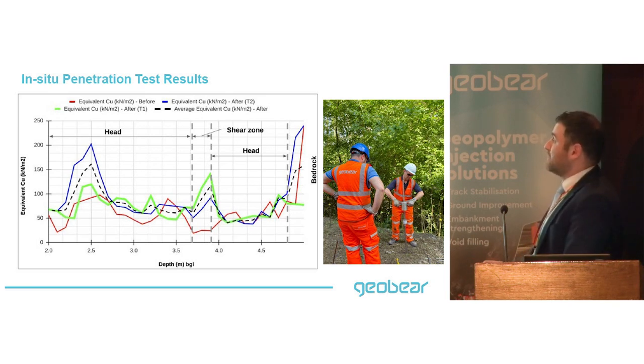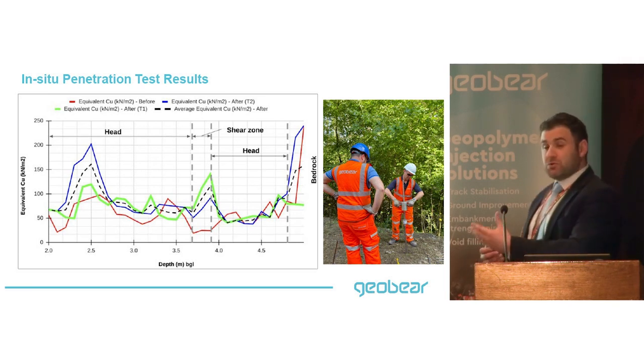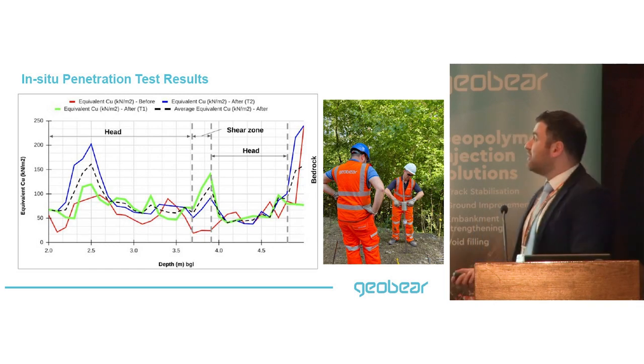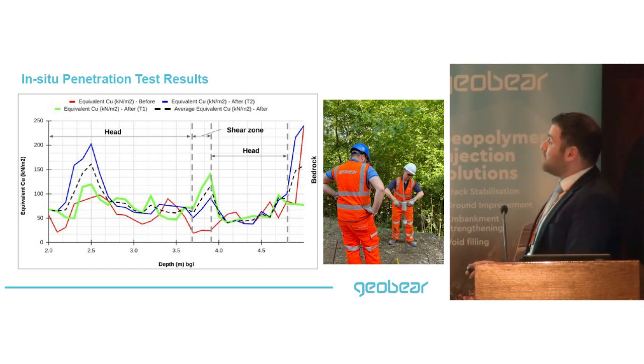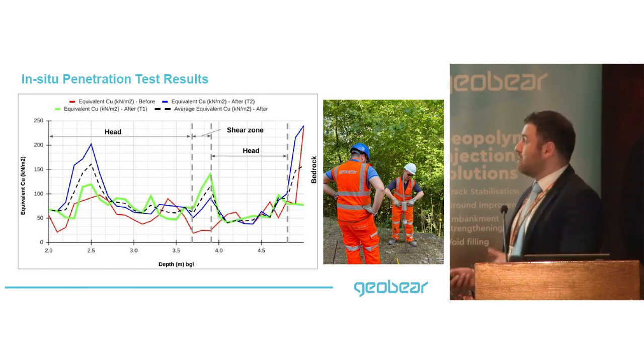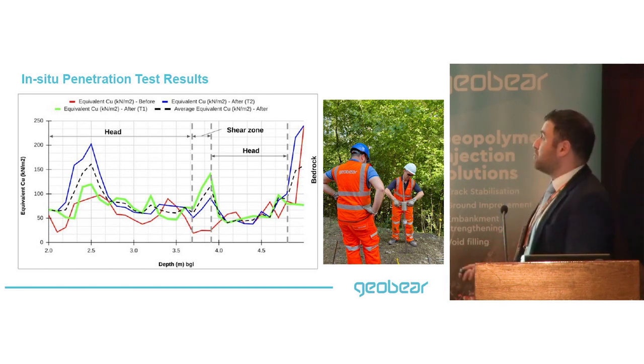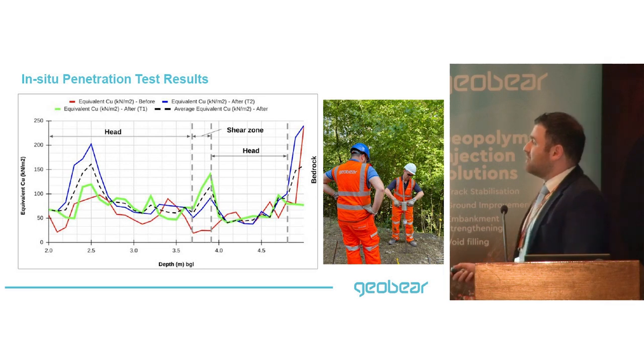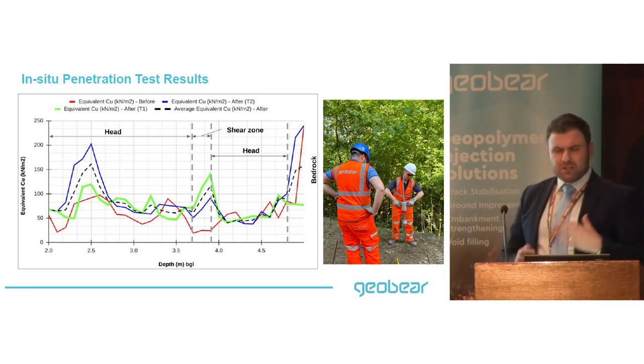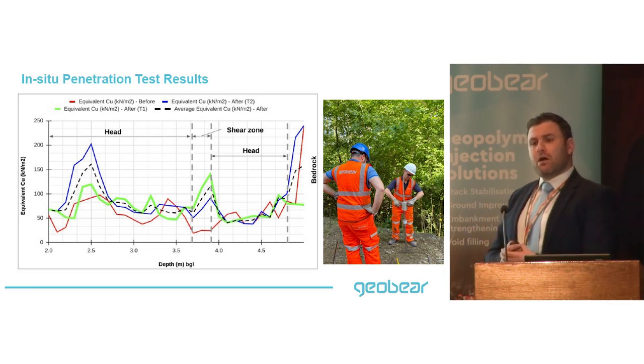We also did some injections within the mudstone on top, the weathered mudstone, and you can see a significant improvement in shear strength there too — from about 100 kPa to about 160 kPa. So a significant improvement in terms of shear strength.